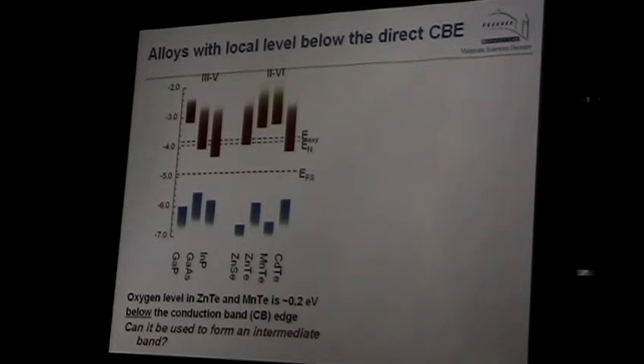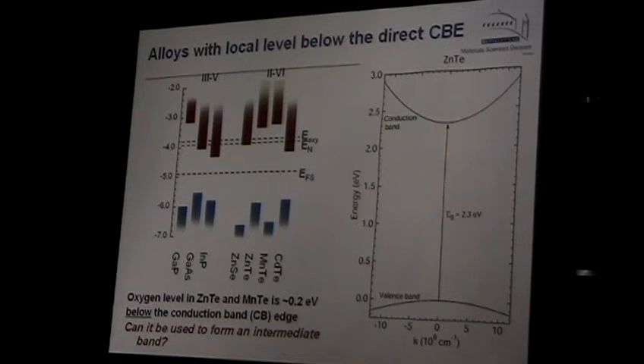And this is a very interesting situation because right now, what will happen with this interaction? We said this was an anti-crossing interaction between states of oxygen and the conduction band. So now what happens in this case? Of course we can do calculations of this and predict what will happen. Basically, this is a cartoon version of zinc telluride. It has a gap of 2.3 electron volts, with a valence band and conduction band. Now we put in a small amount of oxygen, and we produce a level here. We know where the level is because people studied very small concentrations of oxygen alone. So we put the level about 0.2 electron volts below the conduction band.